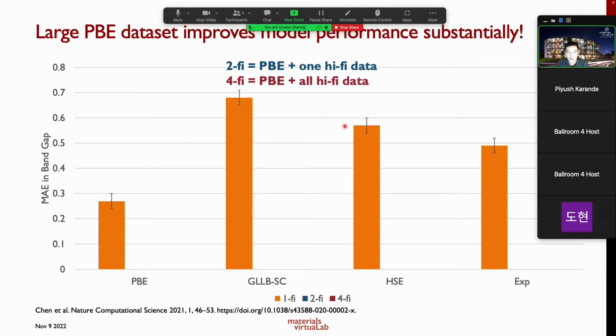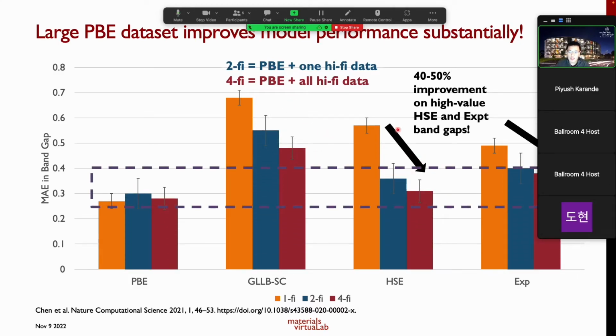And does this work? What we found was that the orange bar shows the mean absolute error in the band gap if we train on each data set by itself. For the PBE data, we can get within a mean absolute error of about 0.3 eV or so. However, the mean absolute error for the HSE data and the experimental data is significantly higher, because the data set sizes are much smaller. However, with our multi-fidelity MEGNet models, we can train two-fidelity and four-fidelity models. In other words, we can throw all the data together and build one single model that predicts any fidelity. We can significantly improve the predictions of our HSE and experimental band gaps.